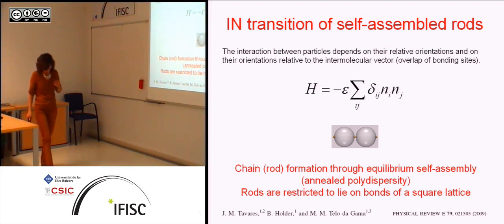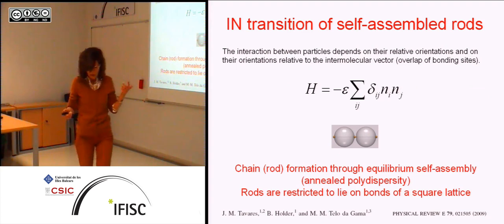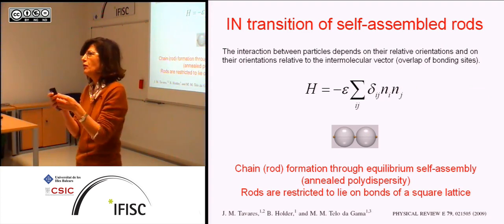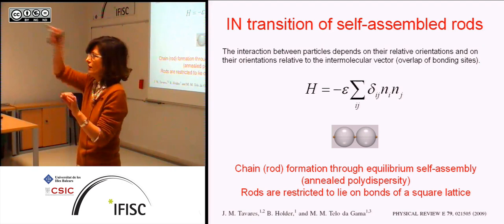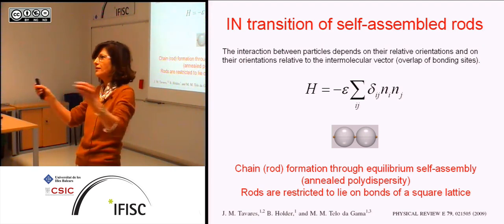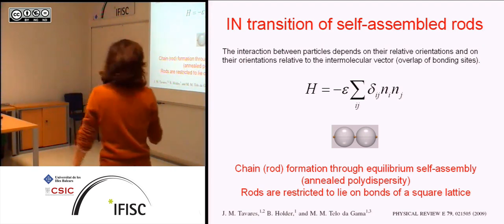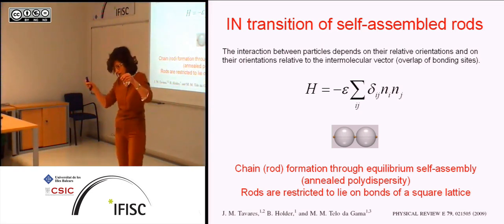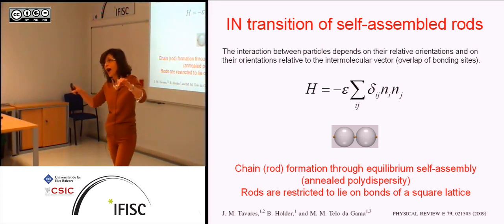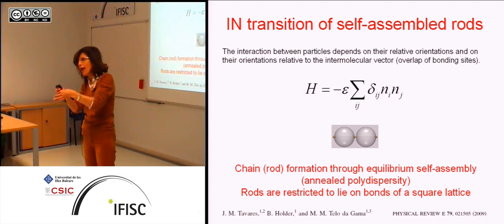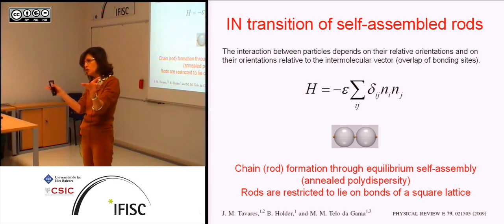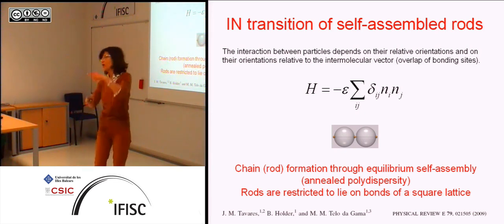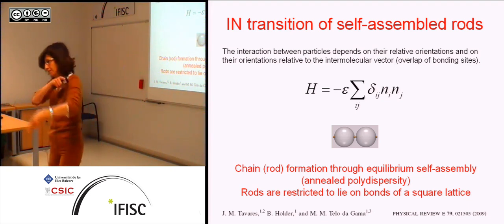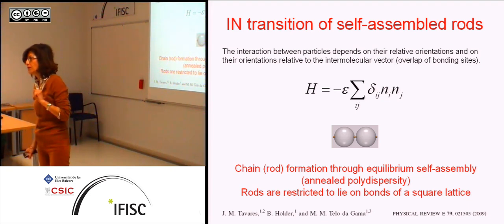So we started with this model. This is not completely historical, but anyway, we wanted to look at these colloids, remember? And we wanted to look at colloids that did not interact isotropically, but they did interact in some sort of an anisotropic way. The most anisotropic you can get is if you put on these spheres just two spots, and you allow them to interact. If these spots overlap, they gain some energy, and so there are sticky spots, only two, and then if you put them all on a lattice, they can only form rods, either up or sideways, but now the length is not fixed.